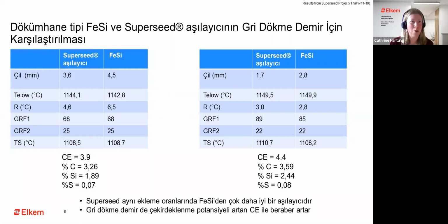The other very popular inoculant used in gray iron inoculation is Superseed, or strontium containing inoculant. And in this slide here, we see a comparison of Superseed versus foundry grade in two types of gray iron. So one with low carbon equivalent, around 3.9 to the left, and one with 4.4 to the right. So you have what we call low or hypo and hyper or eutectic gray iron.